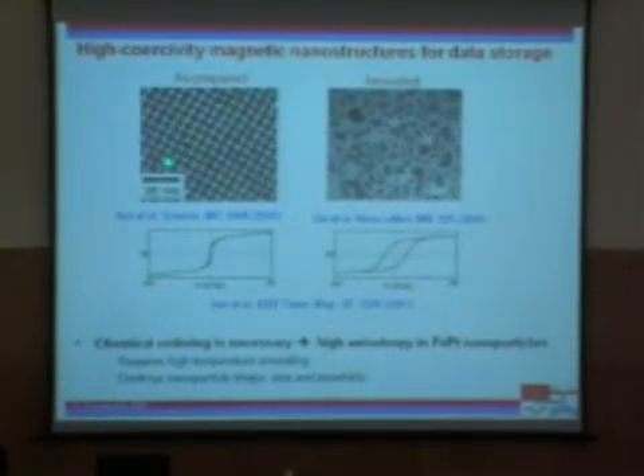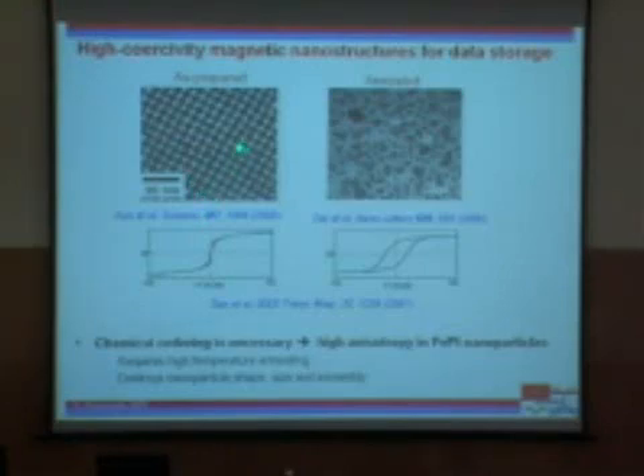So this is actually a very pretty picture. You can see that these are nanoparticles of iron platinum, which are supposed to be magnetic, but in this particular case they are not. Or they're magnetic, but they have very low coercivity. Ideally for this to store data, what you would need is high coercivity, so that the spin stays put where you write it. So you'd like a combination of this and this.